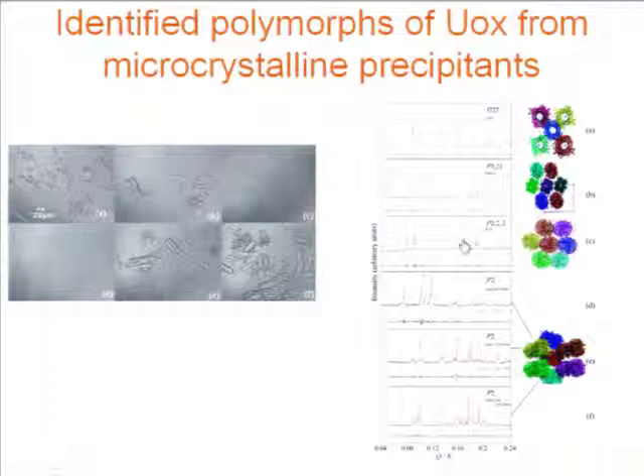We screened a large number of samples which were prepared using different ligands and different pH or precipitant, salt type, and so on. And here you see six different samples which correspond to six different phases, different symmetries. And here are the candidate models which are available in the protein data bank. John already showed a nice table. The problem is that although the first, the orthorhombic phase, gave data up to 3 angstroms, the rest, since they are much larger in unit cell dimensions, gave data from 6 to 12 angstroms. So based on this data, we could only index them and not solve the structure.